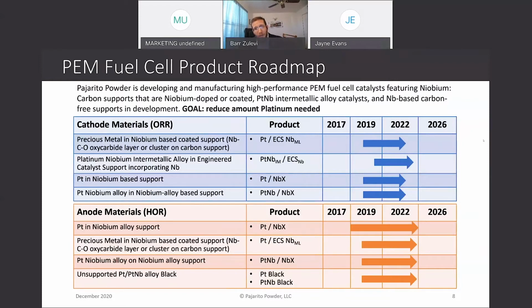use the niobium to reduce the amount of platinum that's necessary to make fuel cells work by enhancing the intrinsic activity of the platinum, alloying or coating or so on, and by reducing the amount of platinum necessary because the platinum is stabilized by niobium-containing supports and structures.